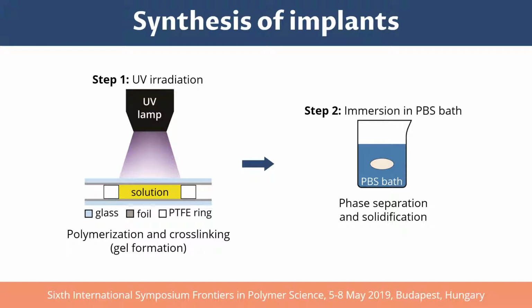Similar synthesis concept was used to synthesize the implants. Now, the precursor solution was dispensed in the mold, constructed by sealing the Teflon ring at the top and bottom with a non-stick foil. The solution was then subjected to UV irradiation to form the gel in the mold. The gel was finally dropped from the mold into a PBS bath to finalize phase separation and solidification of the implant. We then investigated the different properties of the obtained composite reservoirs.